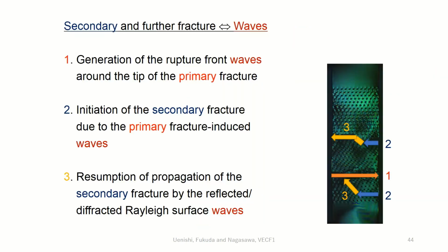The connection between the secondary, further fracture and the dynamic waves can be summarized as follows. Number 1. Generation of the rupture front waves around the tip of the primary fracture. Number 2. Initiation of the secondary fracture owing to the waves induced by the primary fracture. Number 3. Resumption of propagation of the secondary fracture by the reflected and diffracted Rayleigh surface waves.